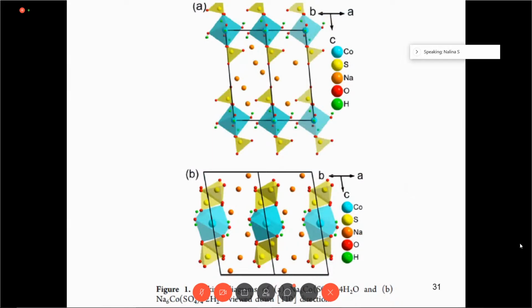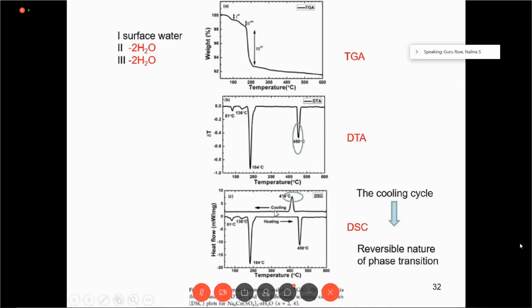The X-ray diffraction experiments clearly suggest that the 2H2O and the 4H2O have sodium ion coordination in these compounds, which essentially can be used to generate a functional material at a higher temperature. These are the structures of the 2H2O and 4H2O. And this is the